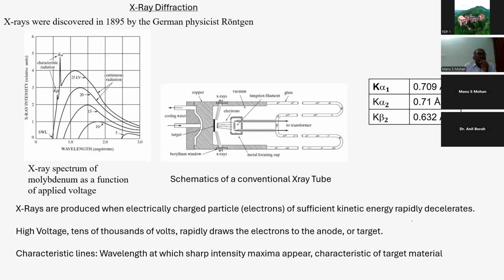So these characteristic X-rays are called characteristic because they are characteristic to the target. For a specific element, there is a specific wavelength for the characteristic waves. So you have the K alpha and K beta. The K alpha 1 and K alpha 2 here are for the moly target, whereas for copper it is 1.54 angstroms. So you can see something like K alpha 1, K alpha 2, K beta 2.